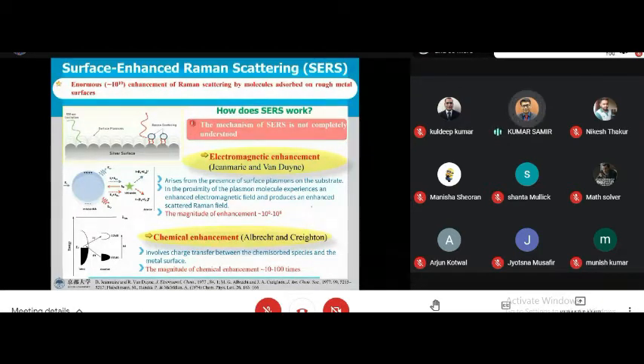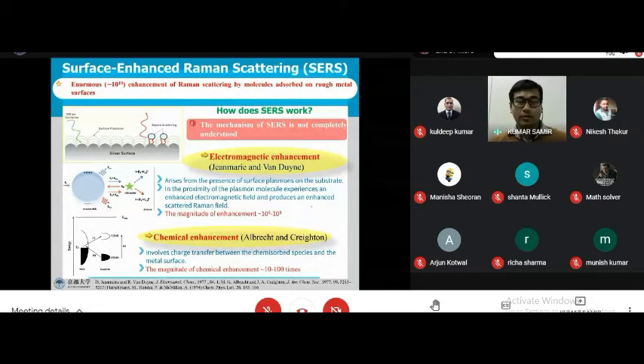The theory of SERS: the SERS phenomenon is not completely known, but there are two major theories that are widely agreed upon about the enhancement mechanism. One is the electromagnetic enhancement mechanism and the second is the chemical enhancement mechanism. And the major contribution is from the electromagnetic enhancement, that is due to the surface plasmon of the metal and the dielectric surface, or the localized surface plasmon of the metal nanoparticles.